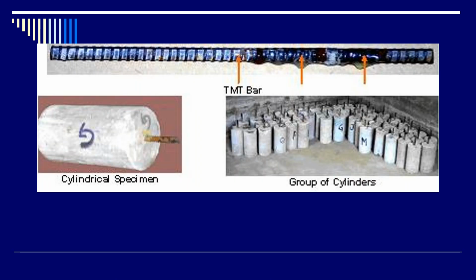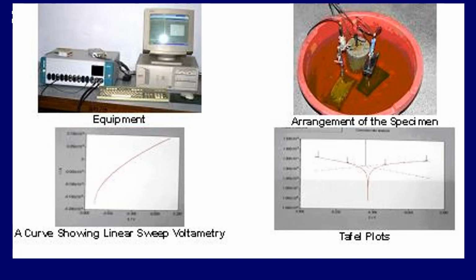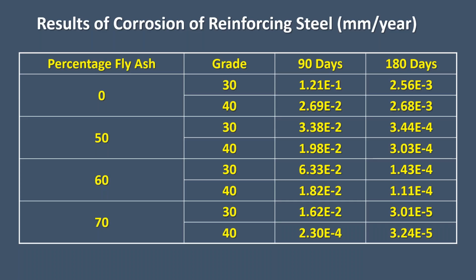You can see that I have embedded reinforcement bars within the concrete. These are the cylinders, and I tried to find out the rate of corrosion at 90 days and 180 days, for plain concrete and for 50, 60, and 70% fly ash. And you see that at 70% fly ash, at 90 days, the rate of corrosion is very, very less compared to the plain concrete. At 180 days, you can see that the rate of corrosion is very low compared to the plain, 100 times less. So we have to properly consider these performance parameters in the design of concrete mixes so that we can rationalize our concrete mixes.